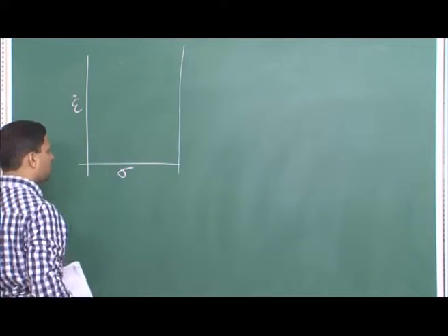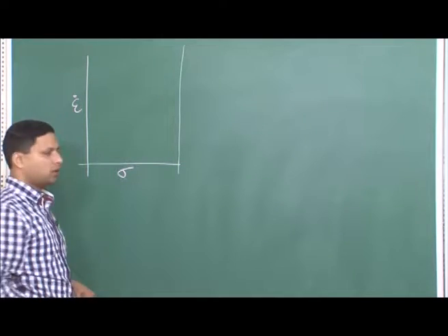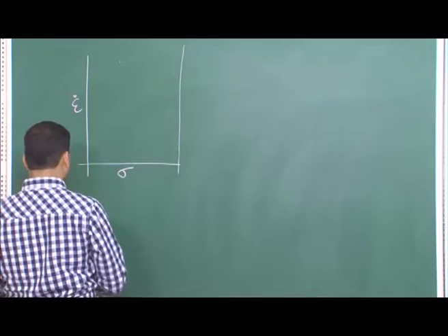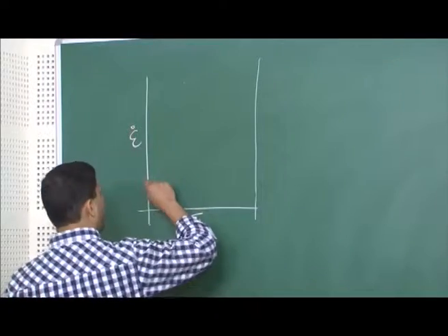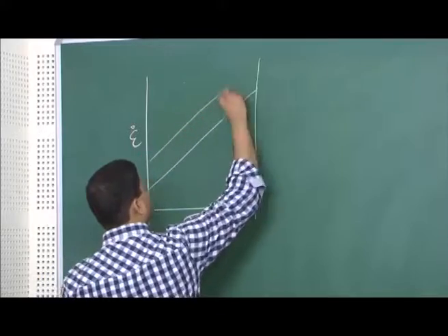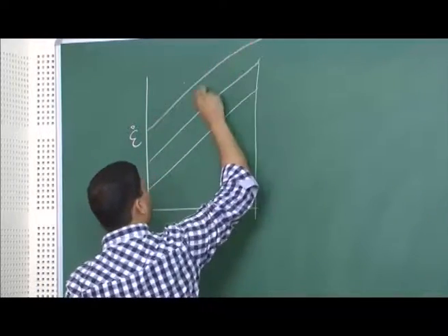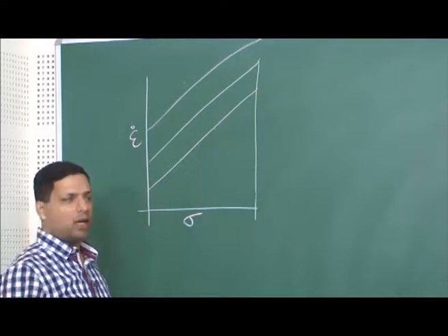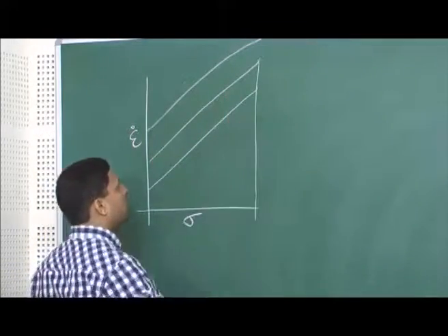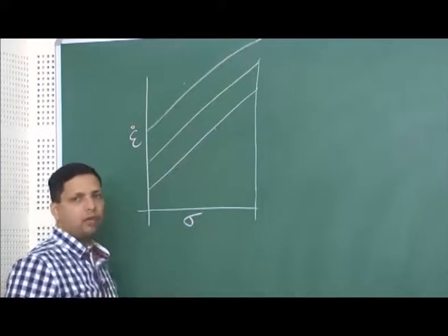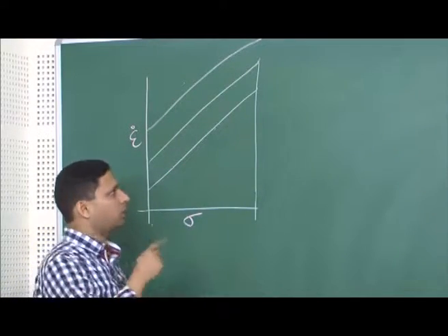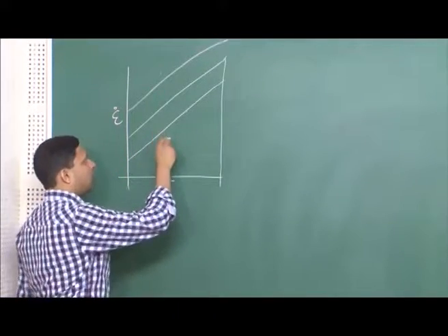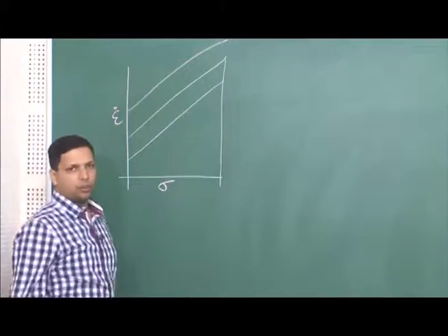So, the plot for strain rate versus flow stress in this kind of experiment would come out something like this. You will have more or less straight line data. These are basically data points, and I have combined those to get one straight line. There may be a little bit of variation in the slope, because again you will see that slope is related to Q, but assuming that in the temperature range we are talking about, the slopes are not changing much.